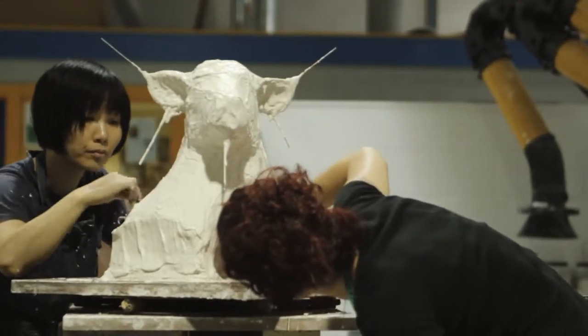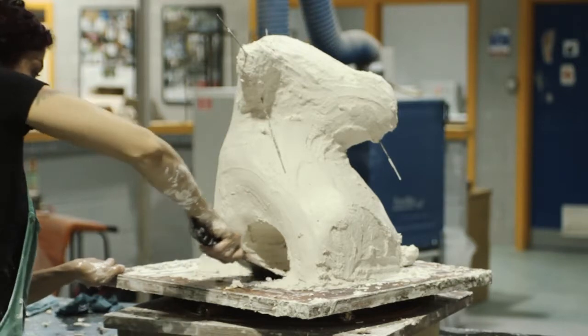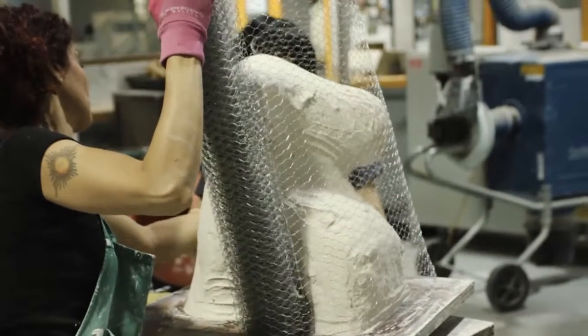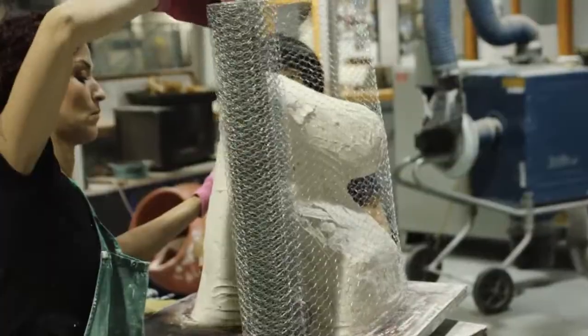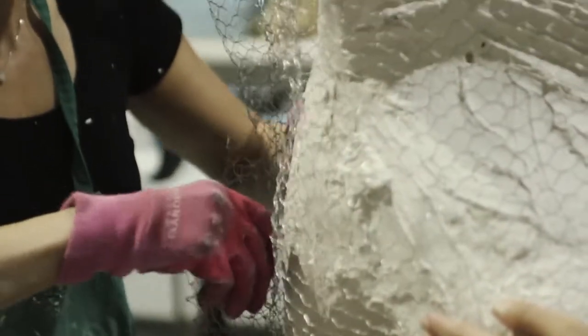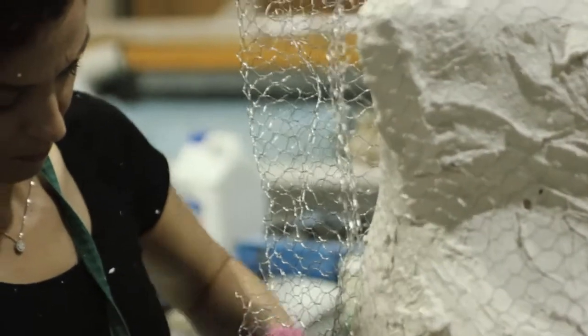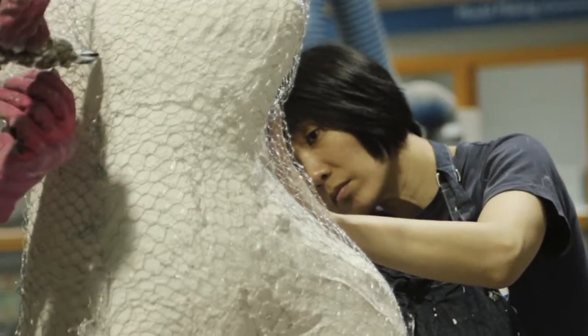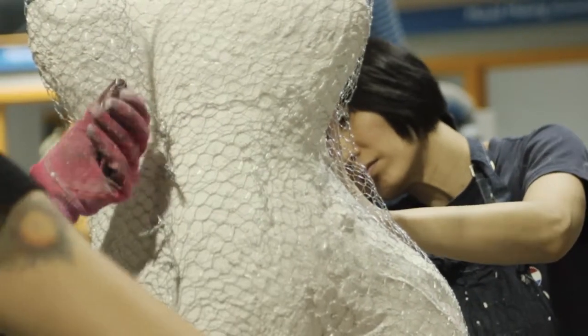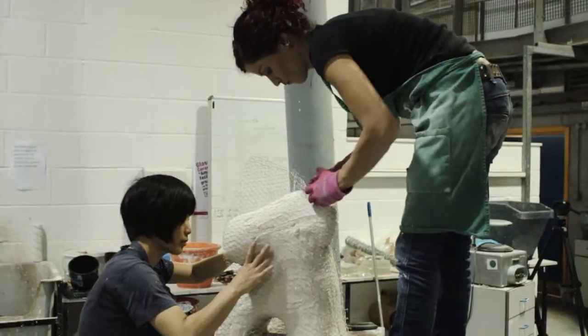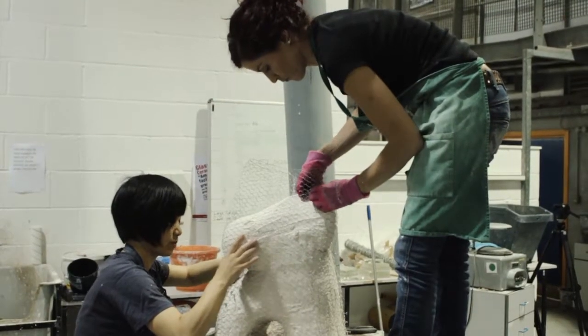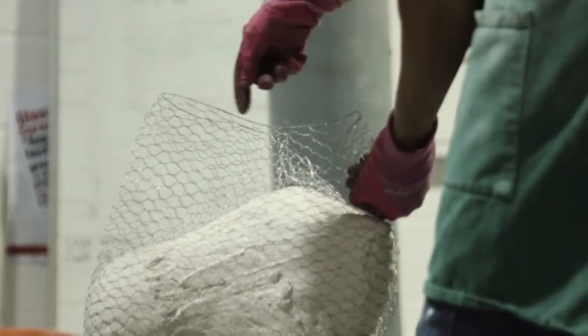And once I have a substantial thickness, then I take chicken wire and I wrap the whole thing in chicken wire. The chicken wire really holds everything together. So because the firing is quite long and the peak temperature is about 820, I soak at 820 for about 13 hours.